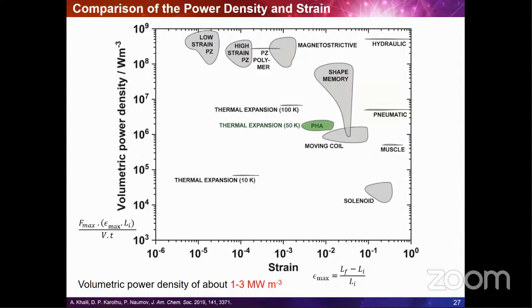You can also conclude that based on the temperature difference between the two forms, these crystals can be classified as thermal expansion actuators. So much higher strain values with similar volume power density can be obtained from these crystals with only a 50 Kelvin temperature rise relative to the existing thermal expansion actuators, which normally require a temperature rise of about 100 Kelvin. Moreover, these crystals can be cycled several times simply by heating and cooling, without the requirement of a mechanically coupled system to reset the original state, which is a very important limitation with the currently used shape memory and solenoid-based actuators. So the thermosalient crystals can also provide the added benefit of being lightweight actuators because their density is significantly lower than that of the conventional shape memory and bimetal-based thermal expansion actuators.